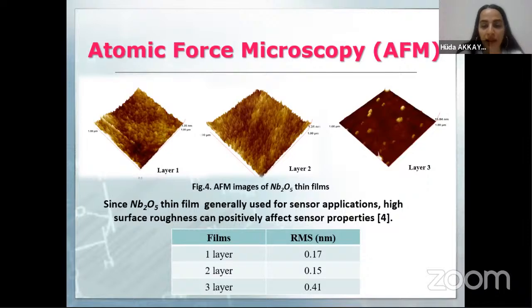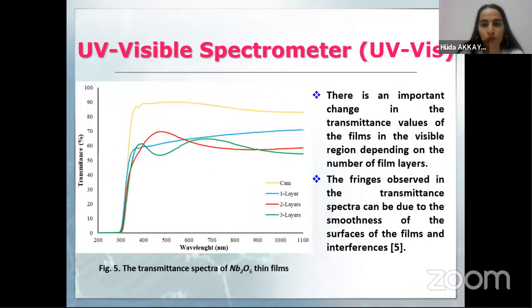Atomic force microscopy: this table shows the niobium pentoxide films' RMS roughness: 1 layer 0.17, 2 layers 0.15, 3 layers 0.41. We see that as layers increase, the surface roughness increases. Since niobium pentoxide thin films are generally used for sensor applications, high surface roughness can positively affect sensor properties. For UV spectrometry, transmittance spectra were measured in the wavelength range of 200 nanometers to 1000 nanometers to determine the optical properties of multilayer niobium pentoxide. We see fluctuation in the visible range of the transmittance spectra, and this may be associated with interference of light at the film-air and film-substrate interfaces, and another reason may be the presence of oxygen vacancies.